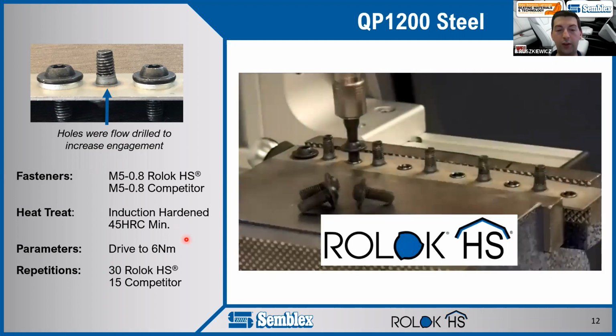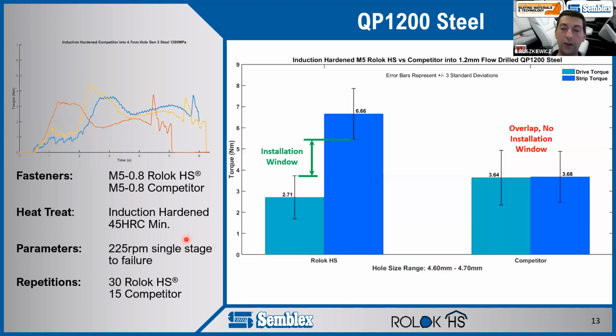For this, we did actually test a competitor's screw. It's not shown in the video, but you'll see the data on the next page. The reason we didn't show it is because the data is more or less non-existent. If we look at the competitor's screw, once again looking at a hole size range, we see that the drive torque and the failure torque are about the same number. I mean, they are the same number statistically. What that tells us is that we didn't form any threads into the steel.